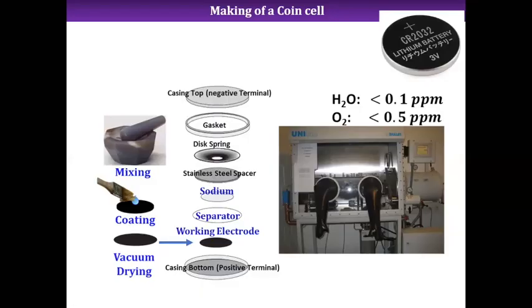The ball milling will give an added advantage, that's true. But my point was, if you get a uniform mixing with hand mixing as well, like many go for hand mixing, so it is well accepted in the field that we go with mortar pestle mixing as well. And sometimes ball milling has this mechanically induced phase transformation. Whatever material you have used, when you are milling it, there are reports on this also, the material undergoes changes if we go for a rigorous milling. So let's say the material is in alpha phase. Now I milled it for 4 hours or 3 hours.